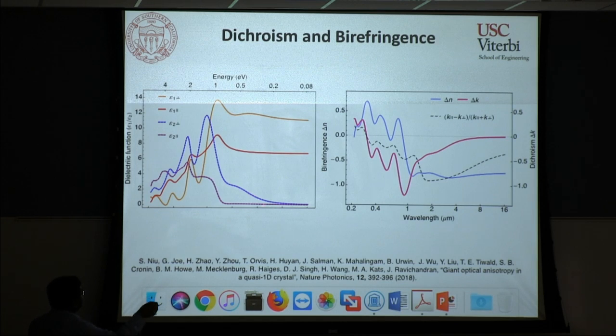Okay, so this is essentially similar to the transmission graph I showed you earlier, and this is the interesting part now. The real part of the refractive index for these two materials along and across the chain are completely different, which tells you that you have produced a highly birefringent material, which has some interesting applications for linear optics and so on and so forth. So we took these optical indices and we quantified the birefringence and also the dichroism, which is how different the absorption characteristics are between the two different directions.